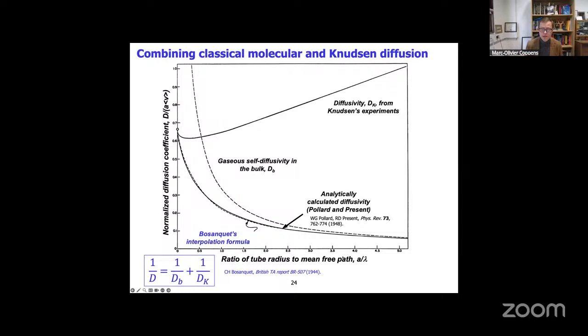And I cite here work that is dating back from the 1940s, right? Because it's still relevant. Pollard and Present, in fact, did analytical work on the diffusivity as a function of the ratio of a tube radius to the mean free path of these molecules, and showed how the normalized diffusion coefficient, so the diffusivity related here to this factor of the local pore radius and the average velocity of the molecules, relates with this ratio of a over lambda.